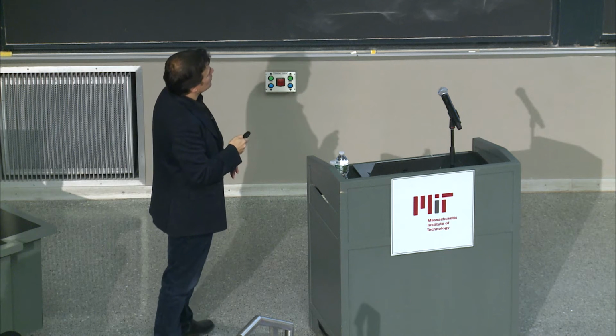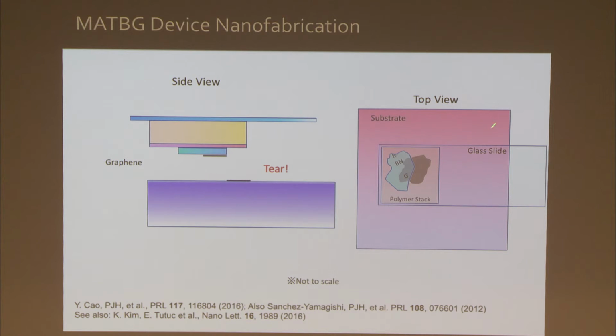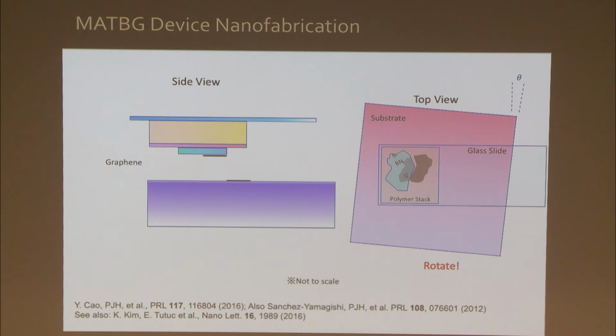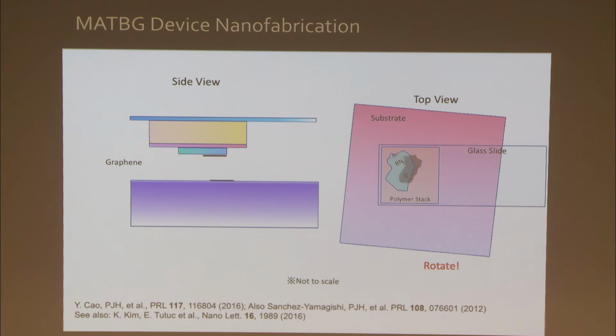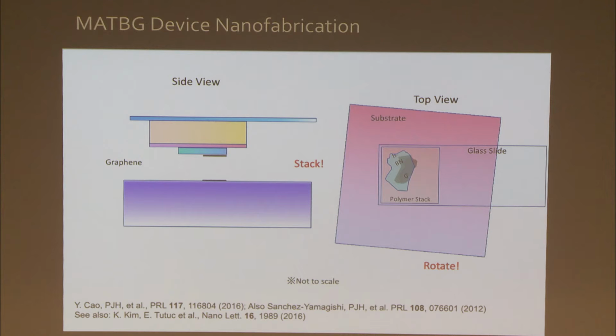Okay? So from the top, we have the glass slide with the polymer, with the boron nitride and half of the graphene on it. And then we have the substrate with the other half of the graphene underneath. Okay? Now, we can rotate the substrate by any angle that we want. For example, 1.1 degree, why not? And then we can shift this on top and we can stack it, okay? And amazingly, we can do this with a precision that produces this beautiful moire pattern at precisely any angle that we want with very high precision, okay?